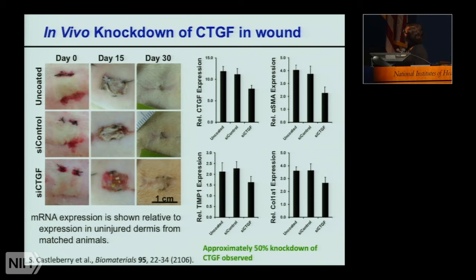So in this work, which is summarized in this slide, we looked at the in vivo knockdown of one of the growth factors in the pathway of fibrotic response. This is connective tissue growth factor. Here we're trying to address a different part of the wound healing process. In chronic wound healing, we had the difficulty of actually getting the wound healing process started, and we needed to get collagen production to begin. Here we have the opposite problem, a kind of overhealing. In this fibrotic stage, the deposition of collagen is accelerated, and we can't stop it. So we're trying to knock down CTGF so that we can lower that fibrotic response.